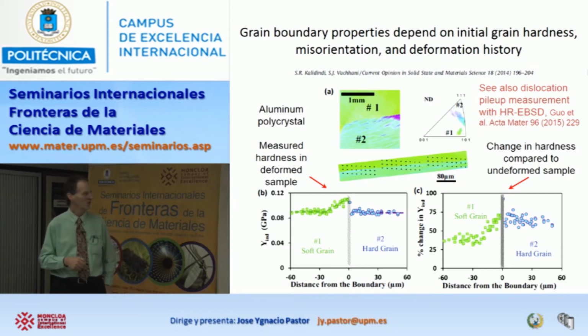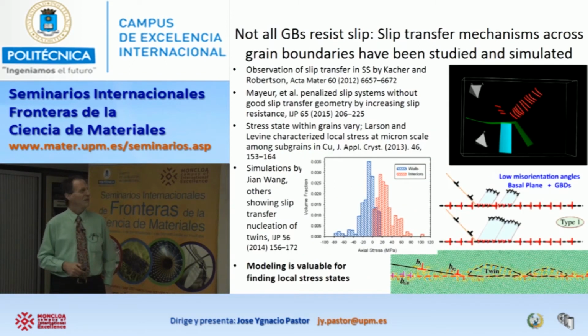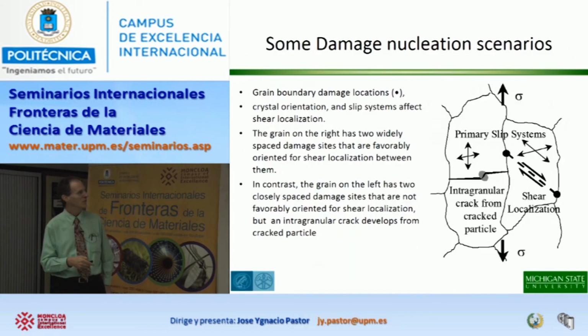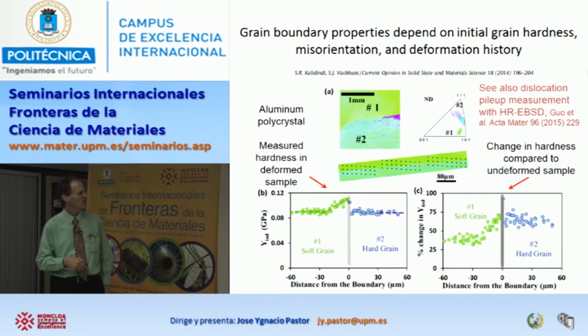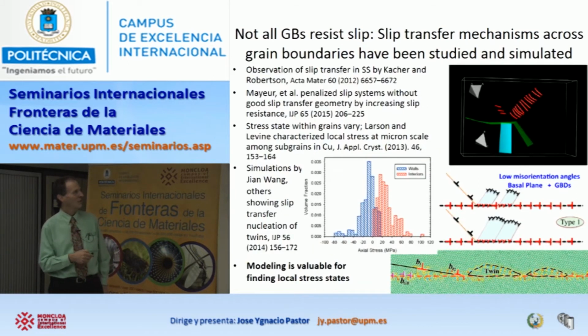So this says that there's interesting things happening near the grain boundary that are different than what's happening inside of the grain. And this just shows how much things have changed from the annealed condition before it was deformed. In the case of the soft grain, it's only increased about 25%, but in the hard grain, it's increased more. And so there's another example of issues that are important to think about. Well, not all grain boundaries resist slip. I mean, this one here suggests that slip is somehow harder near the grain boundary. But not all grain boundaries resist slip.